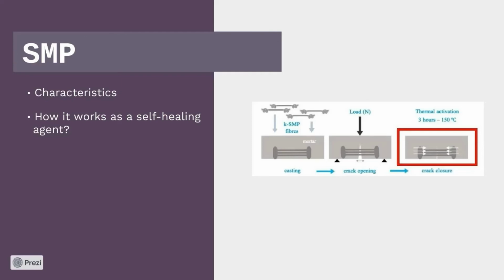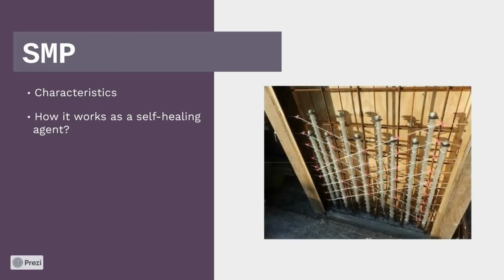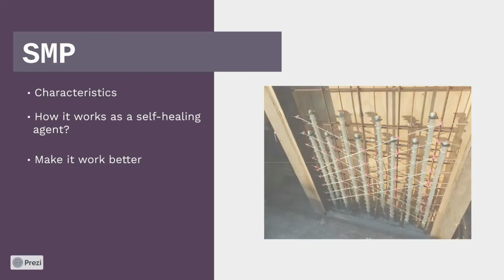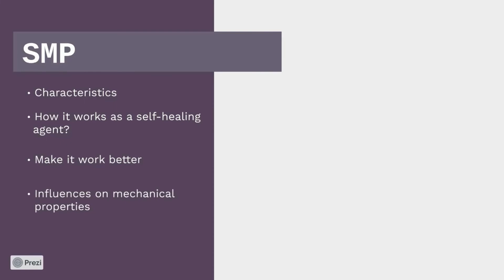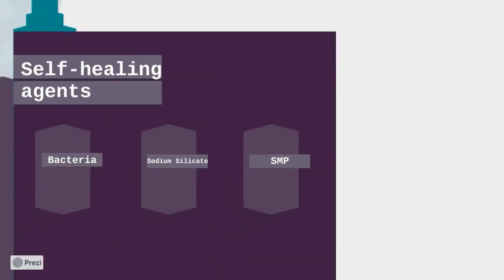Then, if the two knots lie on either side of the crack, the development of shrinkage stresses applies compression on the crack faces, which results in crack closure. It should be noted that if we have a good estimation of probable cracking patterns, these fibers are placed where they can close more cracks and therefore work more efficiently. Using this approach properly proves a better increase in stiffness and ductility compared to other self-healing approaches.